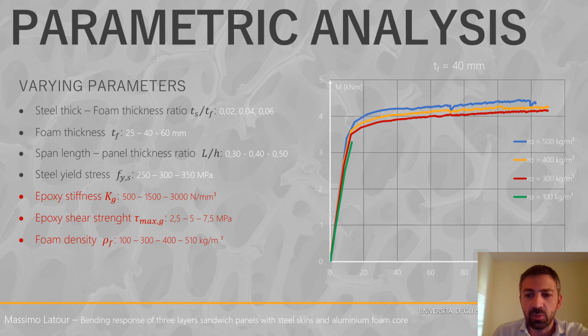The foam density was shown to be very important for the development of the strength of the panel, only when we are considering panels with a density which is lower than 300 kg per cubic meter. So typically densities should not be too small, to allow the failure of the panel in bending and not in shear.